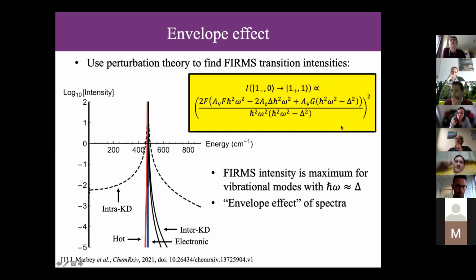But in that case, is it only the resonance that's important, or some sort of coupling also plays a role in the denominator? Of course, the coupling is important. So in the numerator, F and G represent vibronic coupling strengths in this model Hamiltonian. And these essentially are related to the matrix elements of those crystal field parameters, for instance. So it's really hard to link if those vibrations that manifest itself in FIRMS are actually driving relaxation or not, because the physics is slightly different, right? Yeah. Exactly. I am making zero connections between those 2 points at this part. It would be nice to have one.